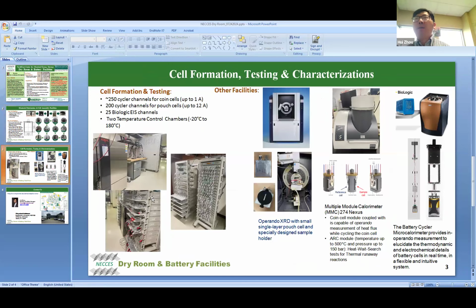So besides the battery facility, we also have some cyclers for the cell formation and testing. For example, we have about 250 cycler channels for the coin cells, which can go up to 1 ampere. And we also have 200 cyclers for the pouch cells. The current can go up to about 12 ampere.